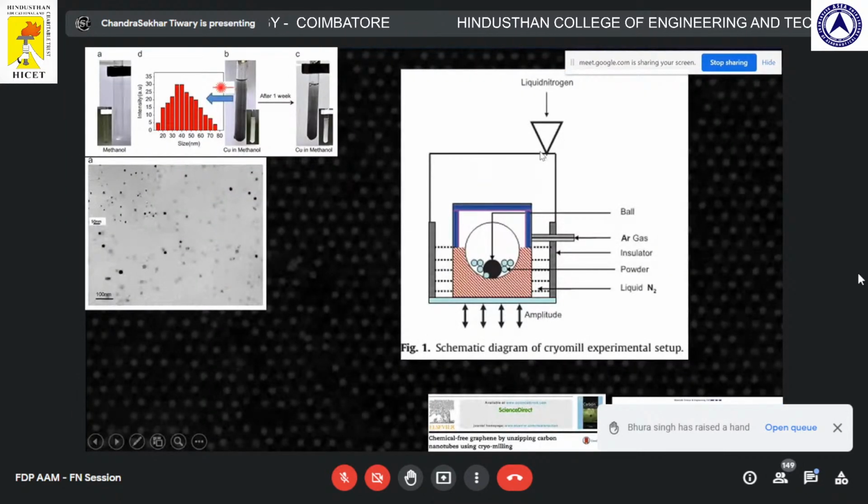We developed a cryo mill, where we take the powder to a low temperature and crush it with this ball mill. With that, we can make nano size. We can go all the way to 2 to 3 nanometer, and make a uniform size distribution with a nice spherical shape. And all these are already patented.